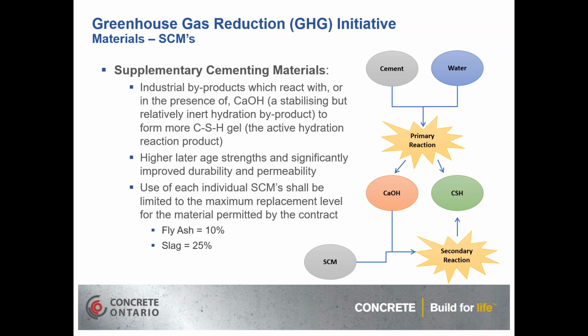So that's why we get those improvements to our later strengths and a much improved durability and permeability of the concrete. Now, each of those individual SCMs shall be limited to the maximum replacement level for the material permitted by the contract. And in most cases, your maximum for fly ash is 10% or slag 25%.